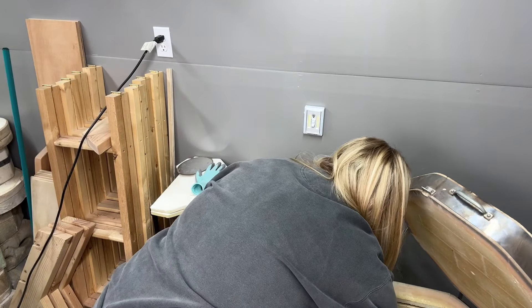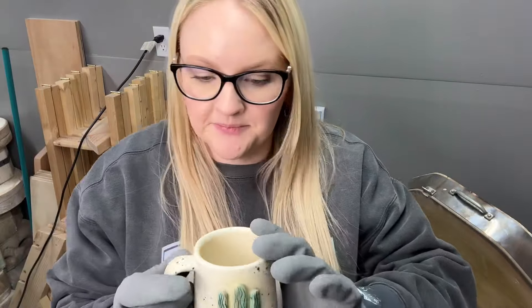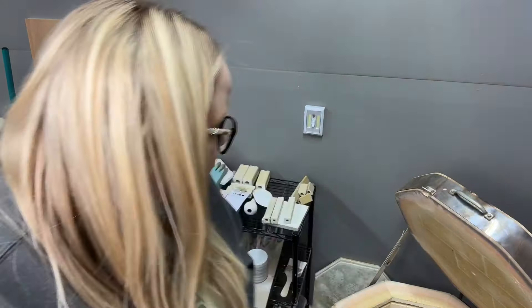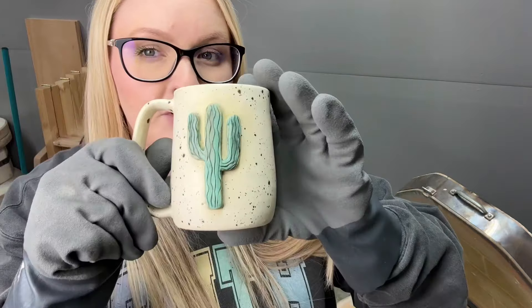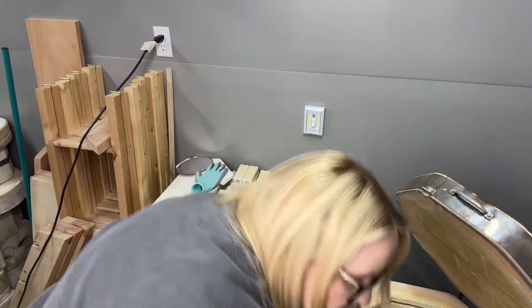Some of the Winter Wood mugs were pinging yesterday but they quit, so I think I'm just opening the kiln a little bit hot. I used up the last of one jar and inserted a new jar, so this is the Winter Wood from the new jar — not as many specs, which somebody might like. The ones that have a lot of specs are the ones that are pinging; the insides of the cups are totally fine.